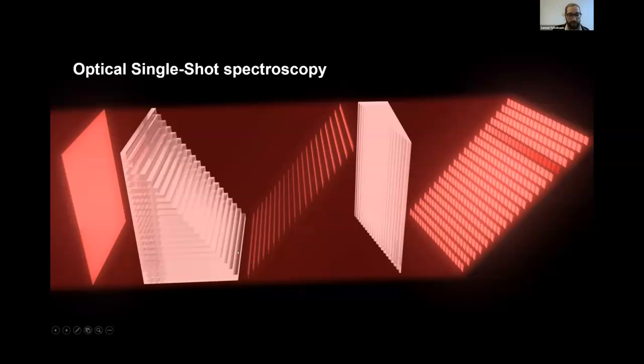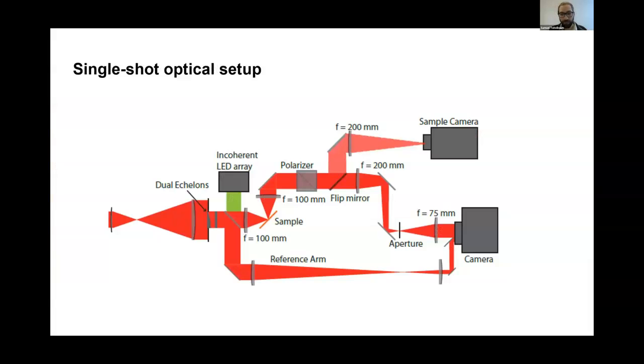And here I'll just briefly mention this. So what you have here is a single ultra short laser pulse represented by this flat square. And then it's passed through a pair of these echelons, which are essentially glass staircases. And what the glass staircases do is the part of the beam that goes through more glass arrives later. The part of the beam that goes through less glass arrives earlier. And by having a pair of them, we can make essentially a 2-dimensional grid of little beamlets that are a 2D array of time delays. By focusing these beamlets onto our sample and imaging them onto a detector, we're able to measure something about the sample.